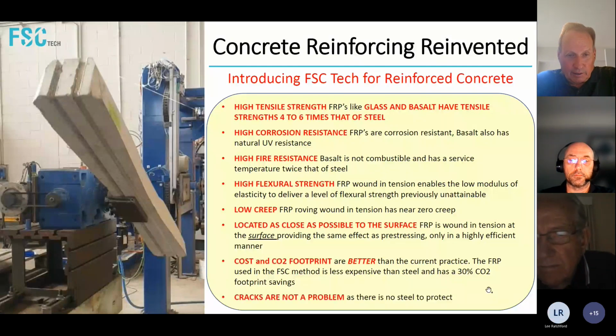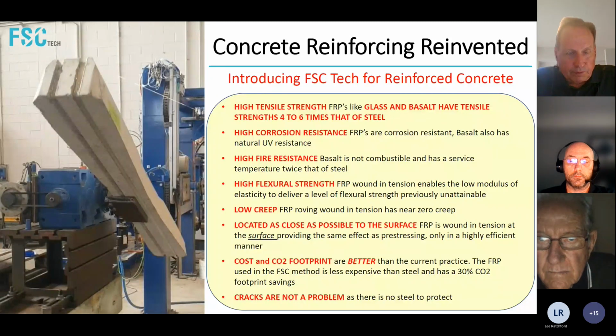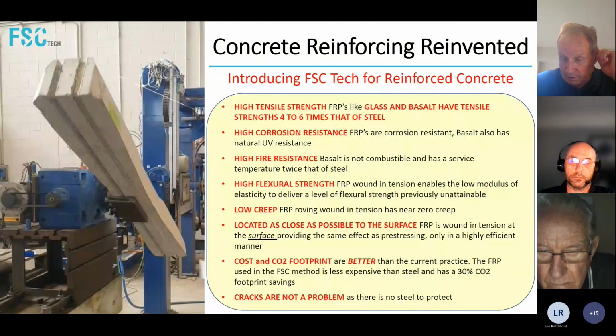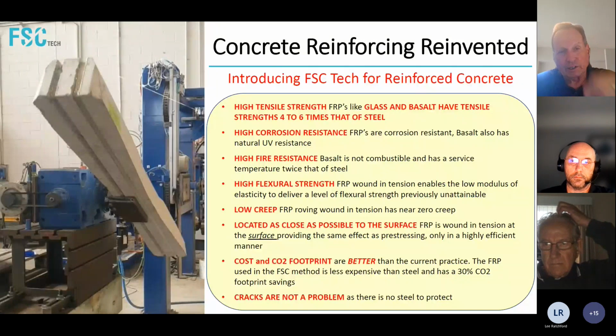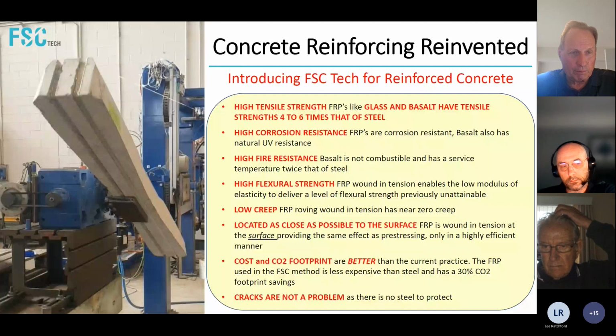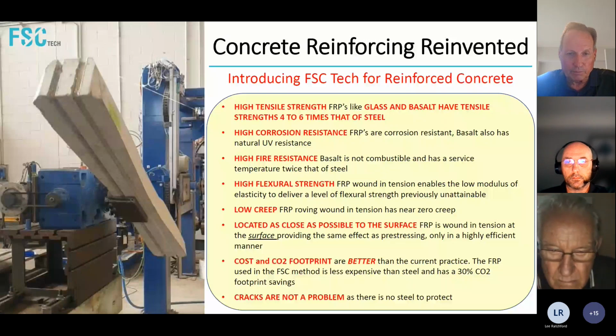And cracks are really no longer a problem because there's no steel to protect, and because you're putting this concrete element into such post compression, if you stress it and you develop a crack, once the stress has been relieved or taken off, the post compression will close it. It will close the crack just like that.